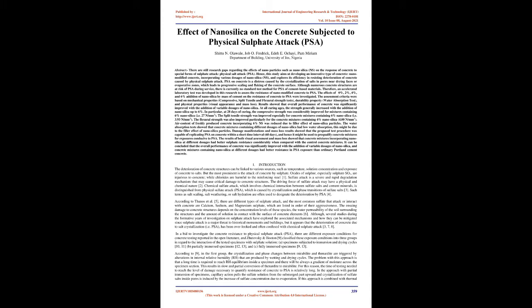The flexural strength was also improved particularly for the concrete mixtures containing 4% nano-silica, 4.00 N/mm². Air content of freshly produced concrete incorporating 6% NS was reduced due to filler effect of nano-silica particles. The water absorption tests showed that concrete mixtures containing different dosages of nano-silica had low water absorption. This might be due to the filler effect of nano-silica particles.